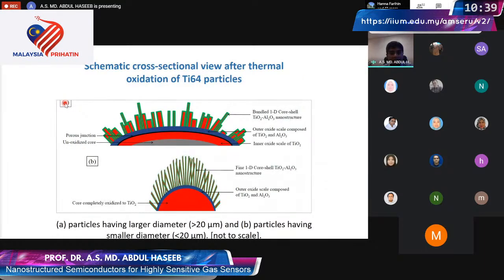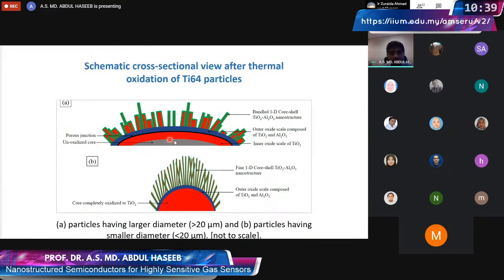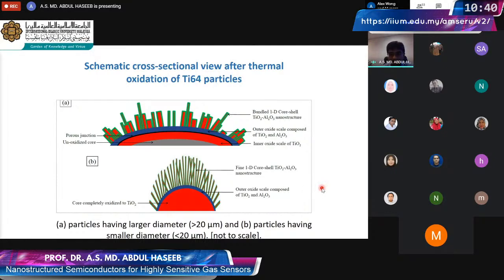And I will just summarize our finding that we have seen. So what we have found out is that if you have a large enough particle, then at the core of the particle, we have unoxidized titanium alloy. And then at the outer surface, we have an inner scale of titanium oxide, which is mainly pure titanium oxide. And then an outer scale, which is a mixture of titanium oxide and aluminum oxide. And on top of this, now we have this nanowire formation under strict conditions. Obviously, when the particle size is small, then the whole particle is oxidized.